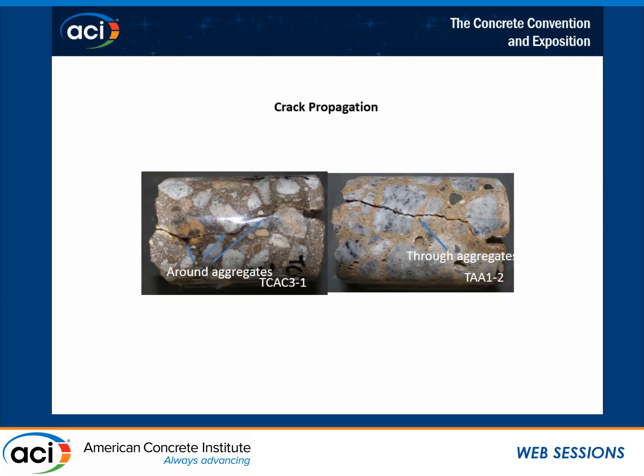Later, and this was after several months of testing, this material went through a phase change, we believe, because it's a calcium aluminate cement, so it wasn't stabilized. Over time, somewhere around 90 days under wet conditions, you get reactions where the crystalline structure of the reaction products changes. So it ends up being a little bit weaker, and we saw that also in the cement-based tests. If we looked at the permeability, the diffusion went up in time, well, the resistivity went down in time, rather than going the other way like everything else.